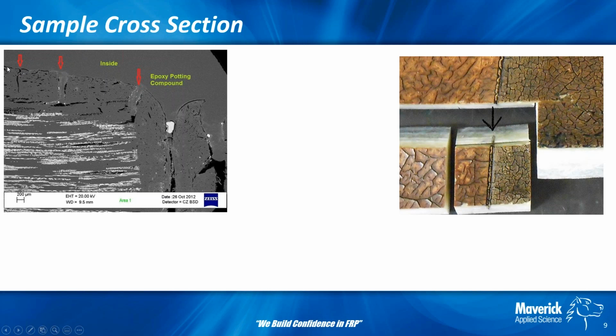But looking a little bit closer, you can see basically the boundary of the corrosion barrier here, and where you see the areas here, this is where the cracks and crevices are that you saw on the surface of the corrosion barrier. Largely, as you can see, this is going down into the veil layer. You can see here that there's that seal, and then the opposite side where it started to come off from that. I guess that's the elbow side there.